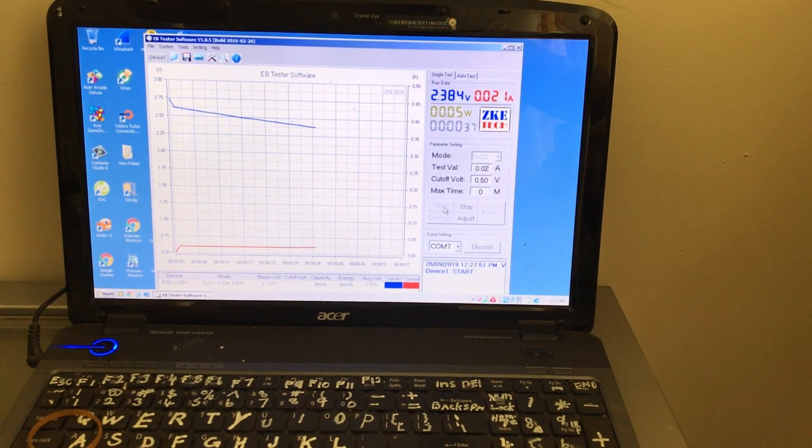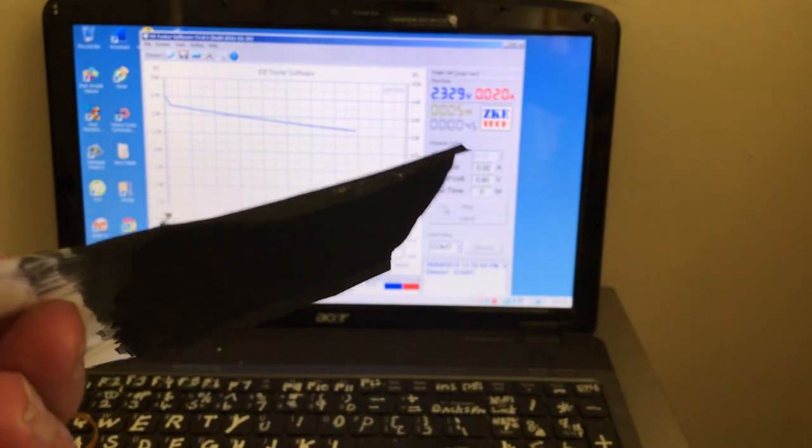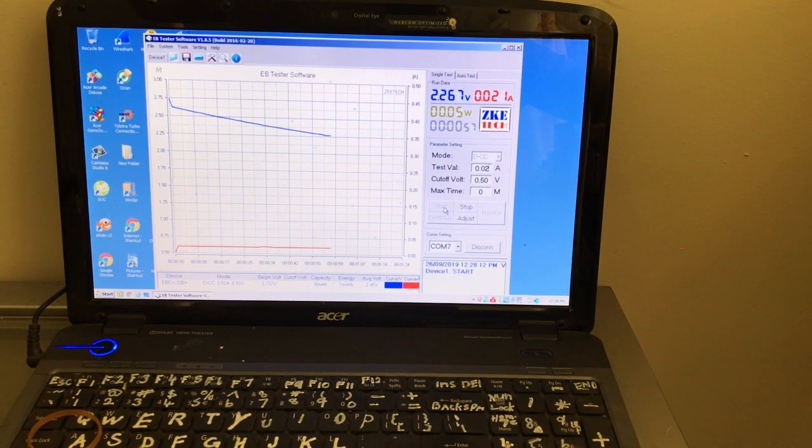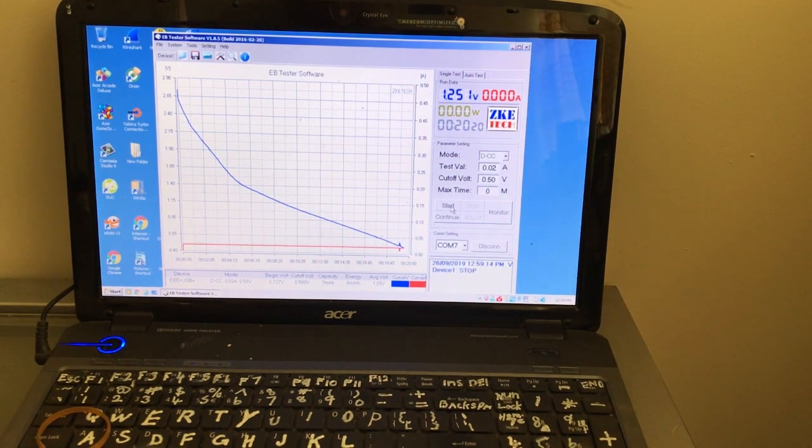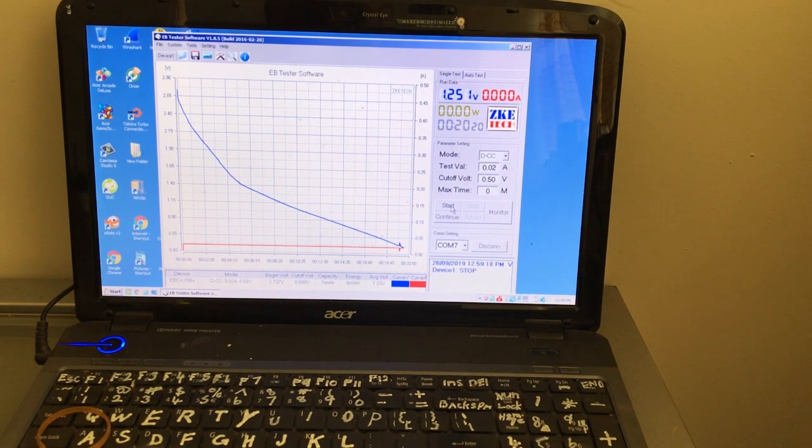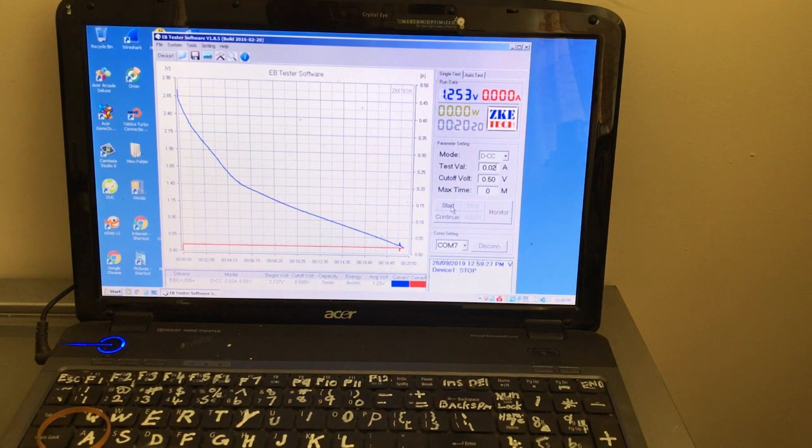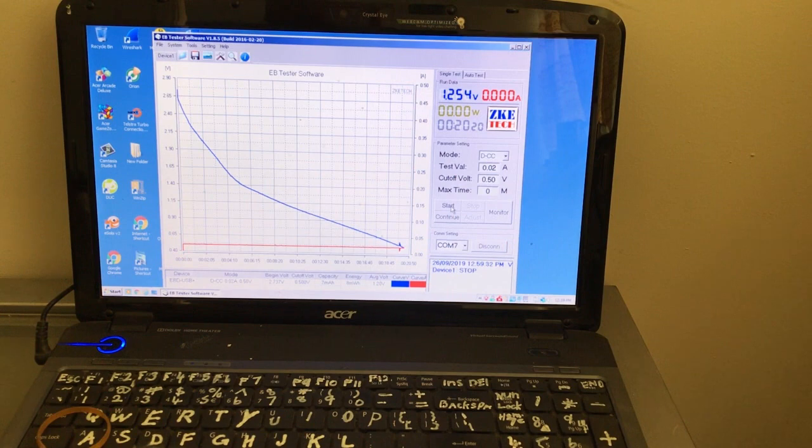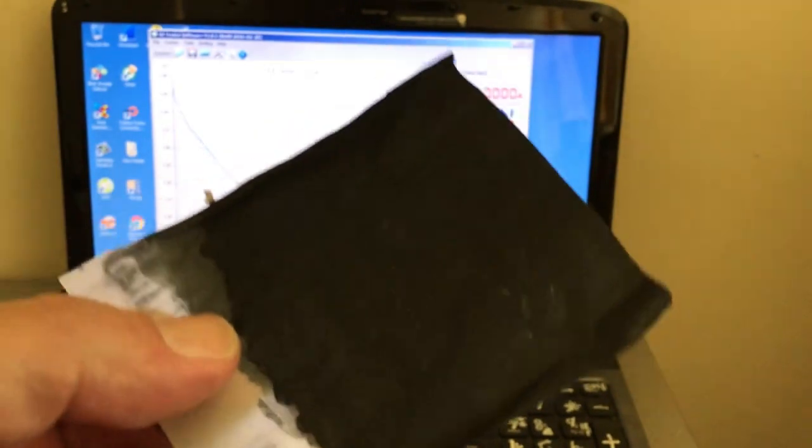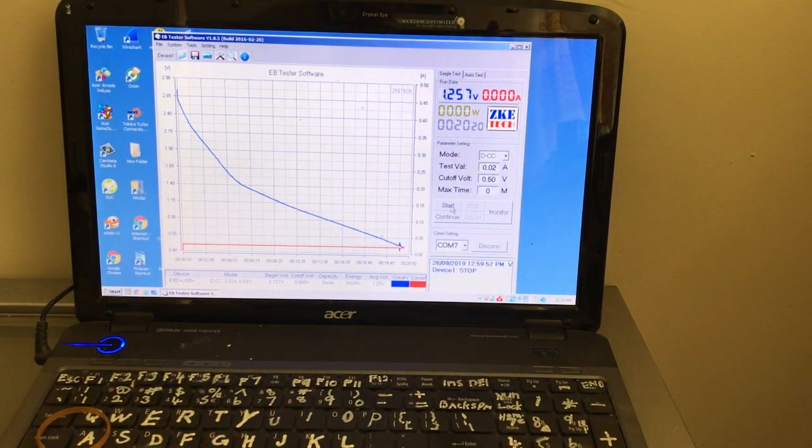Probably don't get as high as voltage if you made separate cells and then connected them. But, eh. And, plus the resistance on this is pretty high. I'm going to try to work on the amount I put in to reduce it. Might even put some graphite powder in there as well. Okay, finished its test. It's still not the 10 milliamp hours it was on the three plate version. But, we're at 1.2 volts after discharge. 20 minutes on the run time. And, 8 milliwatt hours. So, I'll give it another charge. I'll go for 15 minutes. It'll be the last one for the cell anyway. Then, I can concentrate on changing the formula of the paint or ink. It's probably acting like a bipolar plate. Each one of these stacked on top of each other. It's acting as the collector in the electrode joining mechanism.